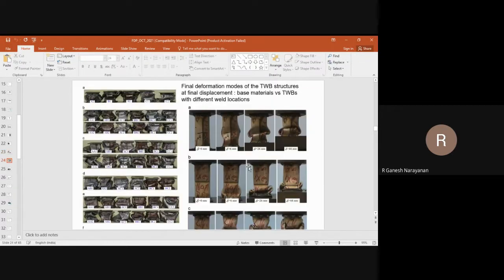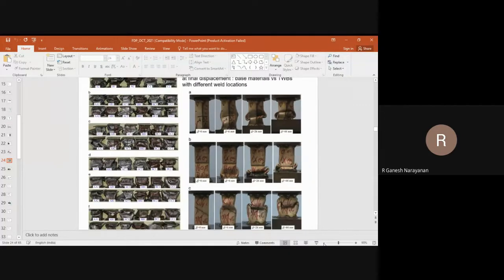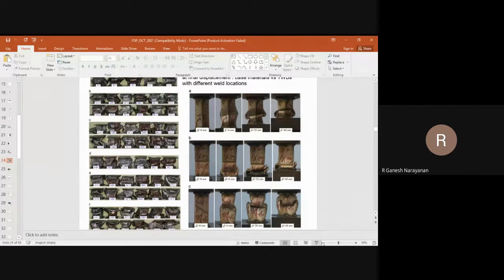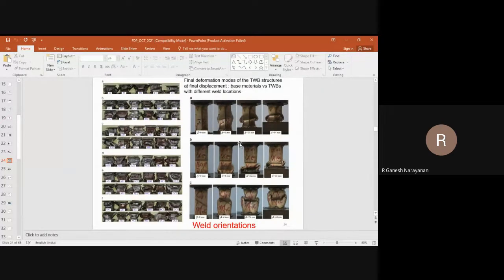how they select material. These are some photographs at different stages. Okay, how the material deforms during axial crushing. And this is quasi-static. This is basically in a UTM, just compress it. And the failure behavior also you see in different stages. You can see different combinations: 0, 6 mm, 26 mm, 44 mm. They take photo shots and they have given you here. Their forming behavior, failure behavior, and the bending pattern also is going to be different. Okay. So one should appreciate the combinations of this, and whichever is acceptable, we have to pick up that kind of material combination and use that for making such type of components.